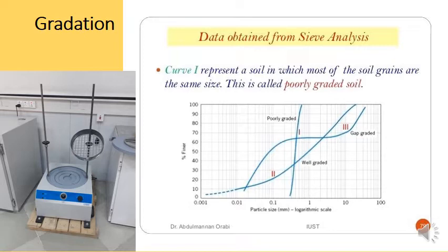Now, if it's poorly graded, all of the aggregate is going to be caught in 1 or maybe 2 sieves, and you're going to end up with a really long straight line where you see 1. If it's well graded, then the aggregate is going to be evenly distributed across all sieves, and you end up with that nice slope, that incline with number 2. If it's gap graded, you're going to get all of the aggregate concentrated in 2 different sieves, a sieve with a small opening and a sieve with a big opening. And that's where we get this step inside the curve. You can see it sort of goes up in a big step. That is an indicator of gap graded.